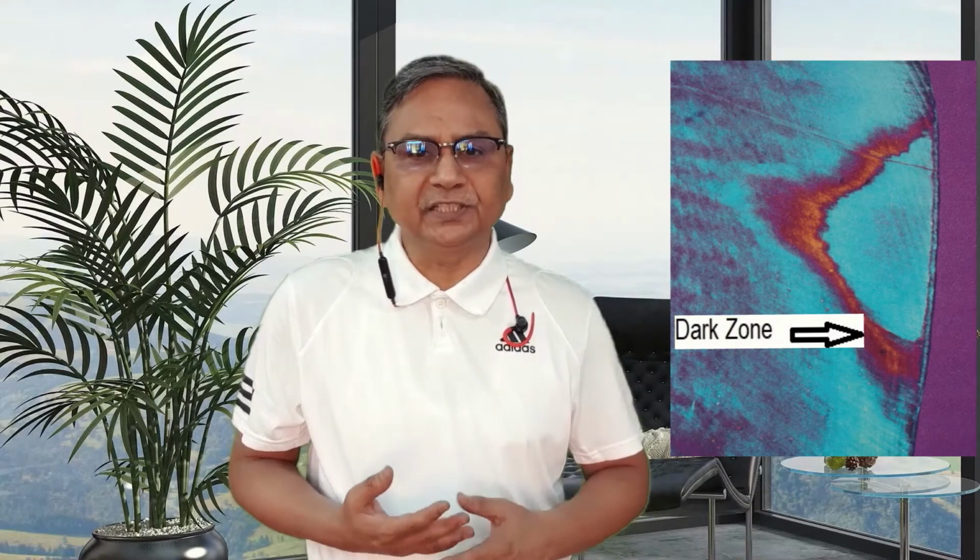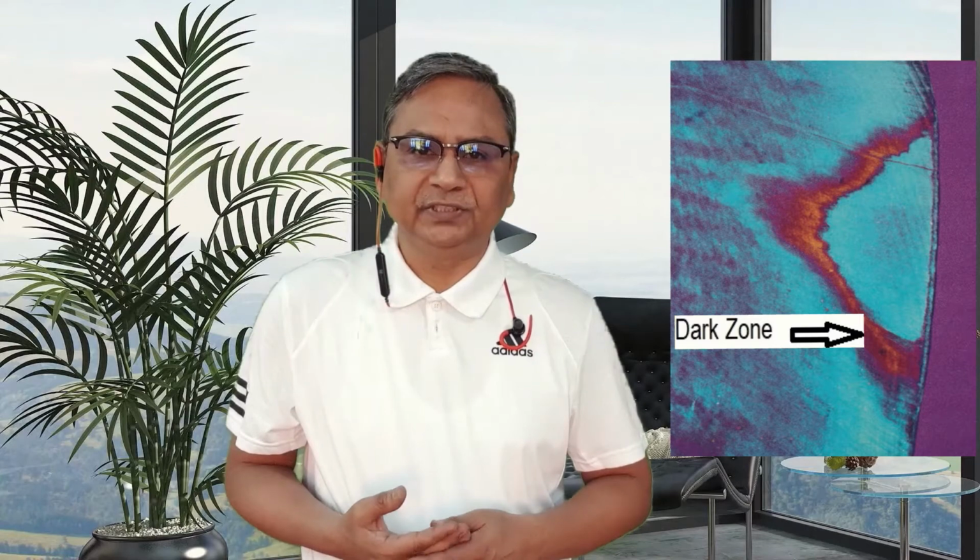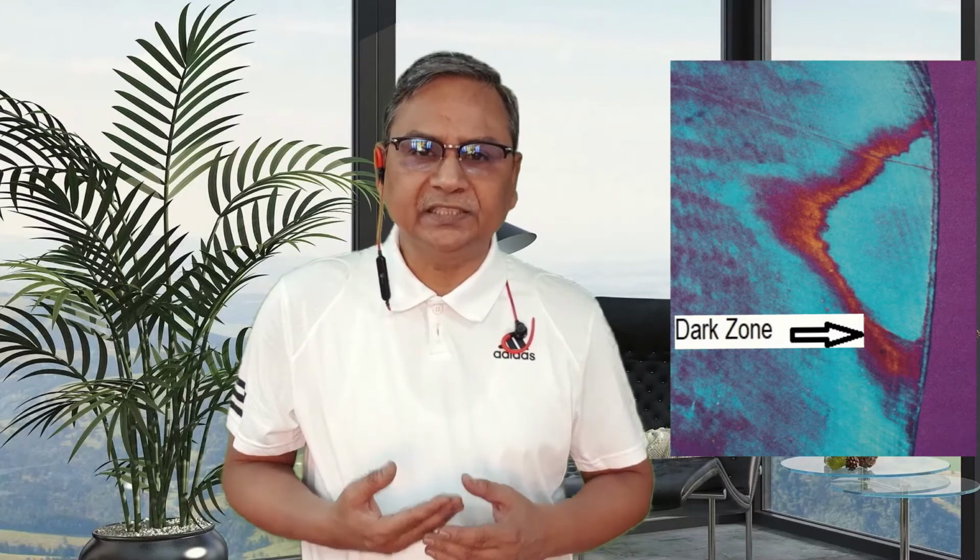This photograph shows early enamel caries. The ground section is being viewed by polarized light after immersion in quinoline. Quinoline has filled the large pores, causing most of the fine detail in the body of the lesion to disappear. But the dark zone with its smaller pores is accentuated.